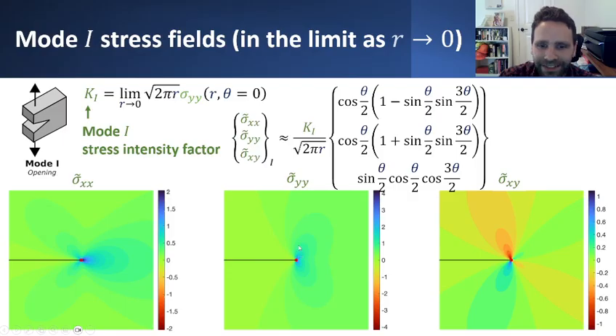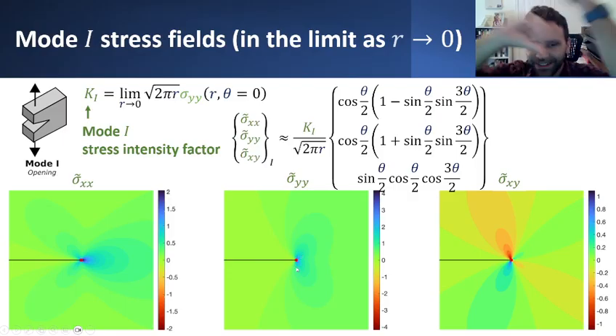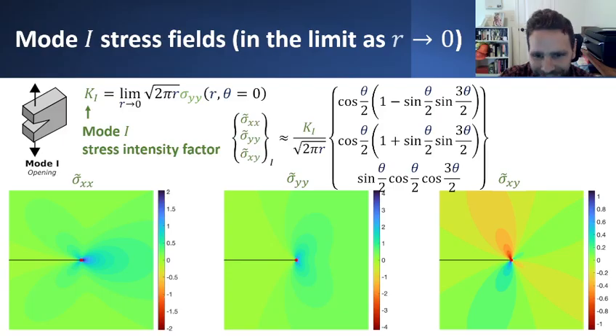Sigma yy, that's the tensile or opening stress that actually drives crack opening. You'll notice it has this funny shape, sort of like a lima bean or kidney bean shape. The stress contours indicate that the stresses also zoom off to infinity. Really, all of these different components of stress, sigma xx, yy, and xy, increase to infinite values as you get closer and closer to the crack tip, but they do so in slightly different ways that depend on along what angular coordinate you're looking.